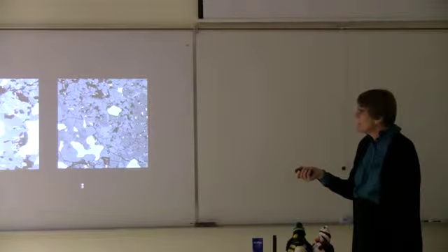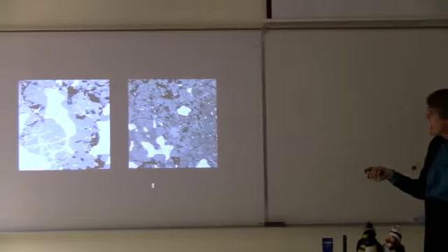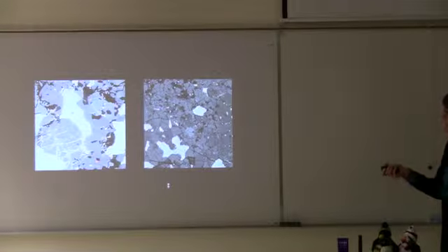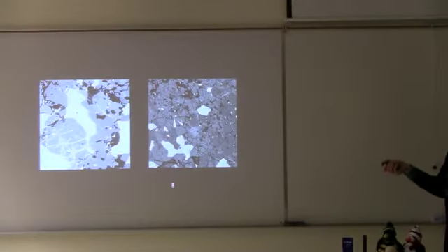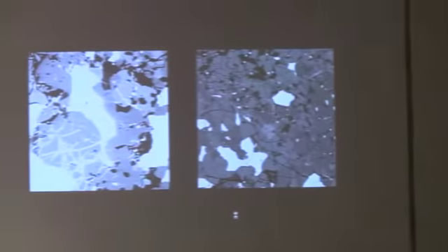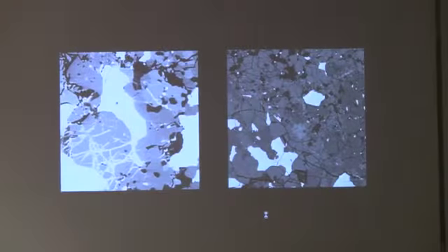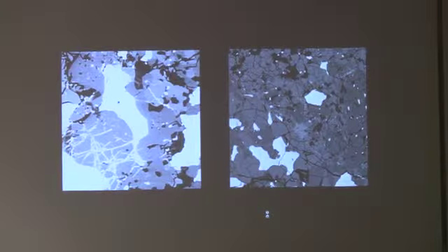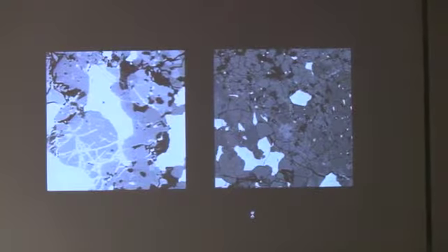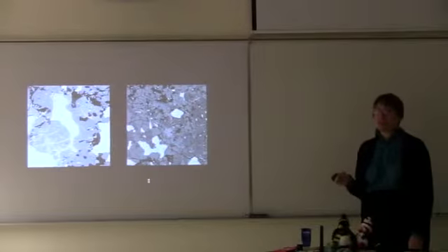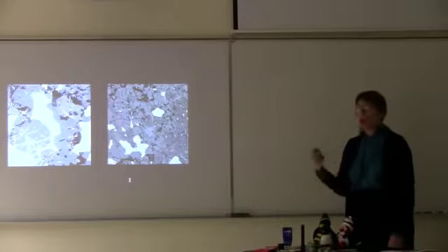And we realized that when you look at these images, I can tell the cracks that are filled with the weathering material as well as the cracks that are empty. So this turned out to be a really clever way to get at measuring porosity in these samples that have been weathered. Because, of course, weathered samples using classic pycnometric techniques have much lower porosities than non-weathered.